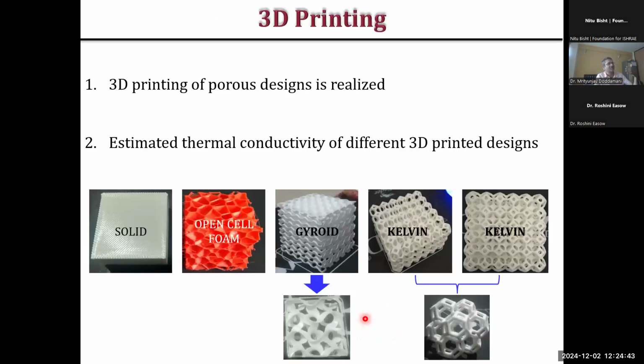Then, based on our simulation and analytical background, we printed different structures. So here you can say this is an open cell foam. This is a gyroid structure, which has basically been used for all structural applications. And this was what our interest was. It's a Kelvin structure. So what we looked into in the simulation has been replicated through a 3D printer here in the form of a Kelvin structure. I have just zoomed out, and you can see an actual Kelvin structure here. So these struts are solid or foamed. That is what non-foamed and foamed means. And this is how the Kelvin structure looks. I'll repeat: the struts, the joining elements which form this Kelvin structure, are either foamed or non-foamed.